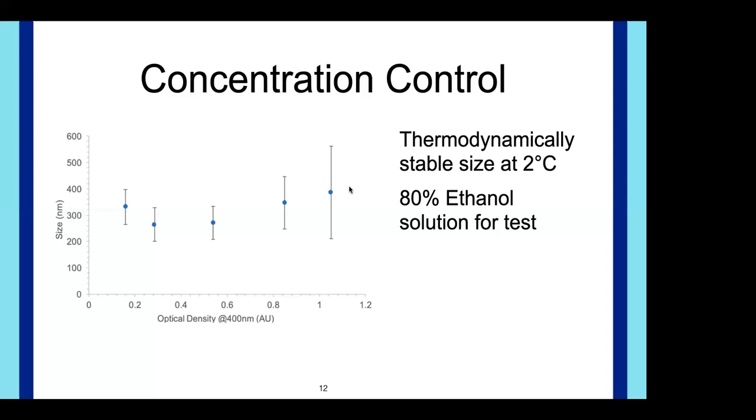With the kinetic control, there was definitely a sweet spot of a certain concentration. You couldn't go too high in order to get these to deagglomerate to actually do a kinetic quench, but you also couldn't go too low because it would take too long for them to agglomerate again, that you couldn't get that short timescale range, and you'd have a lot more polydispersity once you get into the very low concentration based on optical density.